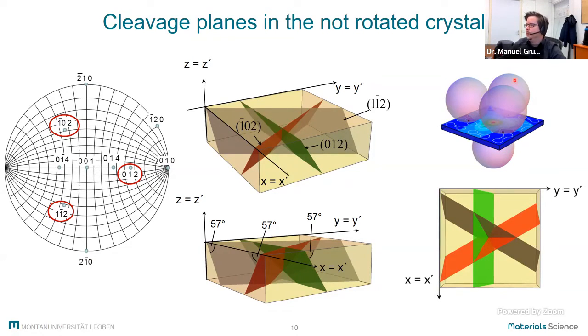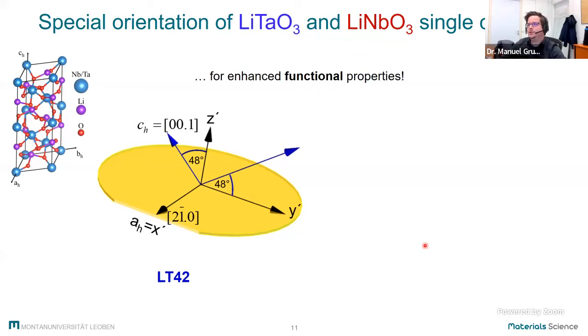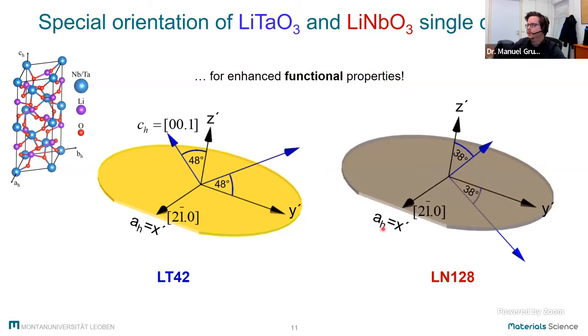And so the fracture patterns should look somehow like this, but this was not what we observed. The reason is simply that to enhance the functional properties, the wafers were rotated for the surface acoustic wave device. So clockwise for lithium tantalate, this orientation is called LT42, and for lithium niobate, clockwise, this configuration is called LN128.